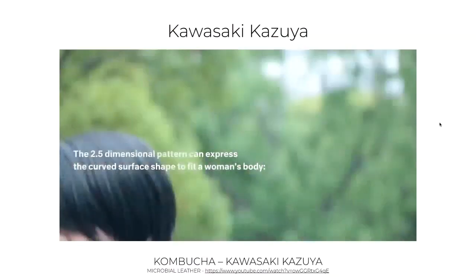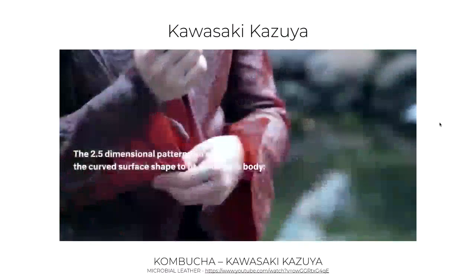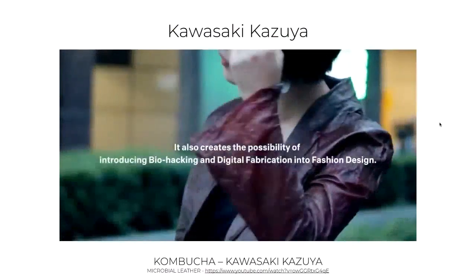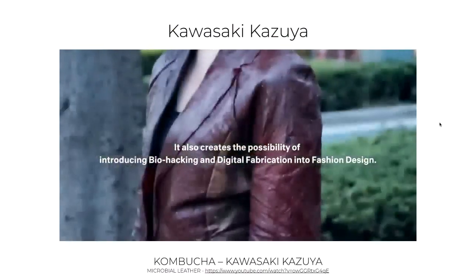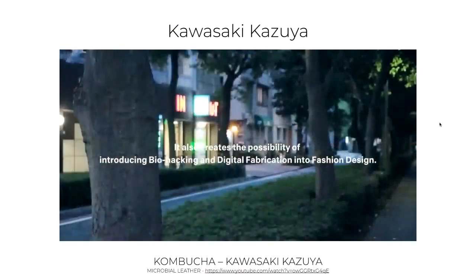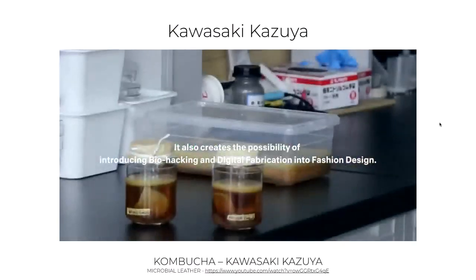It can also very easily be dyed with either natural dyes while growing it, with beets or hibiscus. Everything that is acidic actually works really well with kombucha, so you will get a lot of pinks and reds, and not with the alkaline ones. But what you can actually do is extract the pigments and then use those after, just before drying and just before pre-treating it, so that you can create very colorful materials as well.